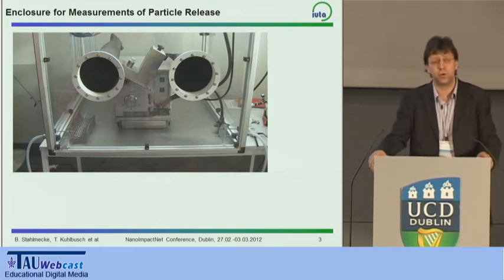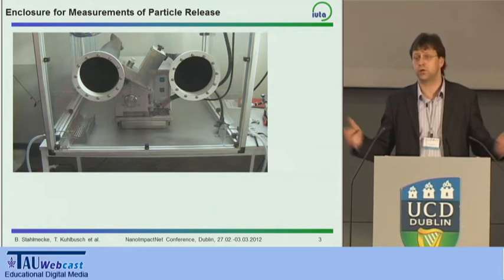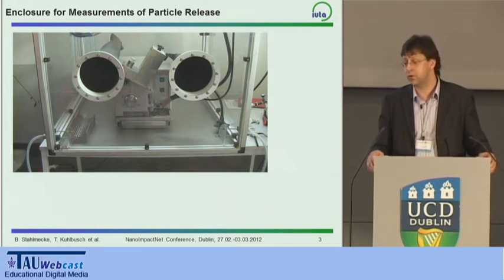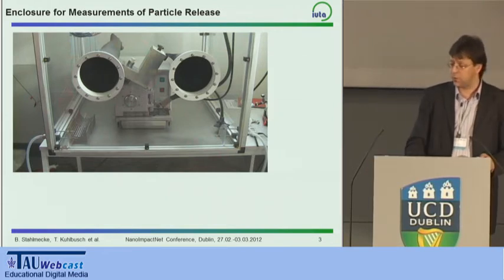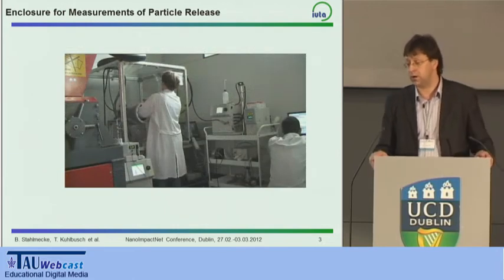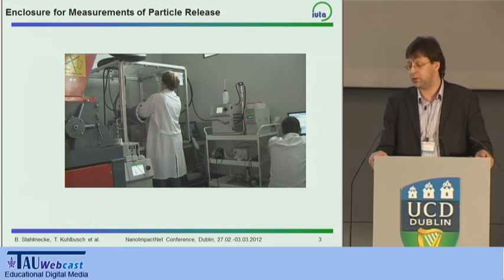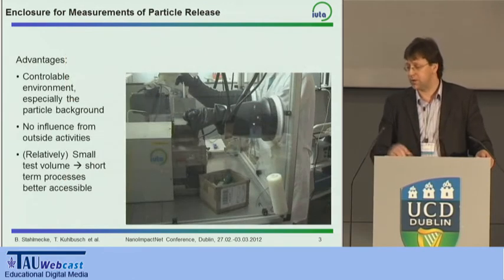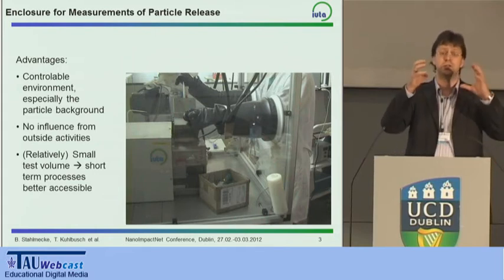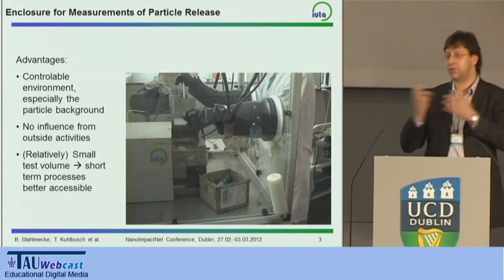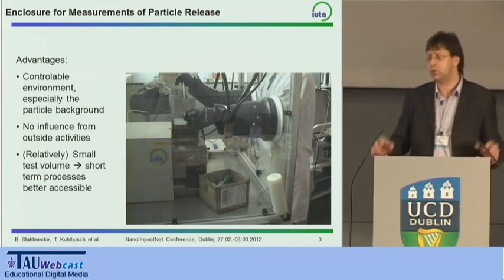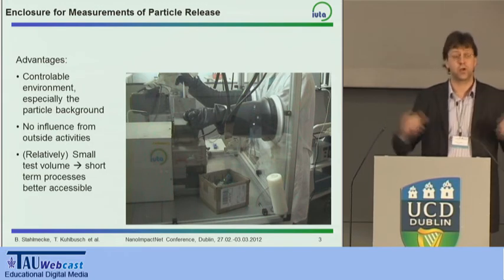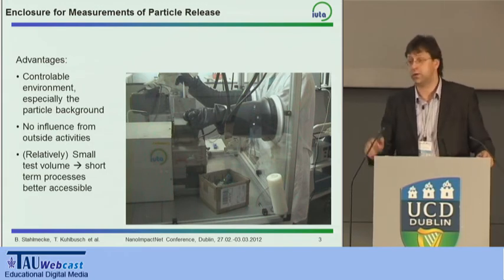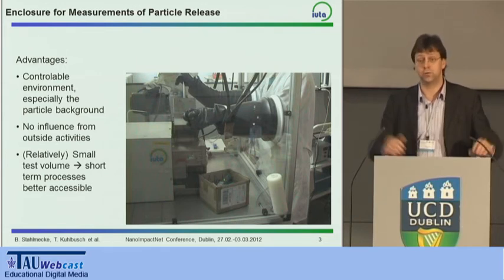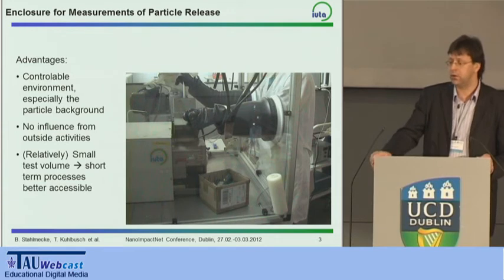It was also mentioned this morning, background particles are a major issue. So the logical thing for us was to put it into a glove box. We put the shredder into a glove box as shown here, which is enclosed from all sides quite nicely. And you see it here in operation, with Daniel actually feeding the shredder. The shredder itself has a disc with sharp edges at the side and a mesh around it. There are different types of shredding systems. This is the type we used here, which is a very small shredder compared to the large facilities for industrial shredding. But that's what we can do within a glove box. It's certainly not easy to enclose the big shredders used in industry.